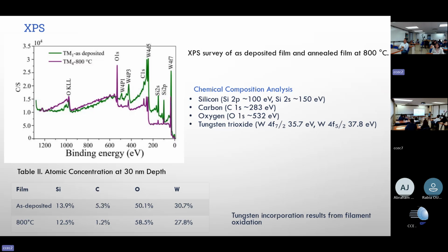XPS is necessary to know the atomic concentration of each film. We can observe that oxygen, carbon, silicon, and tungsten are present. In Table 2, we can observe the atomic concentration at 30 nanometers of depth, where the carbon content decreases, oxygen increases, while the tungsten content is high.